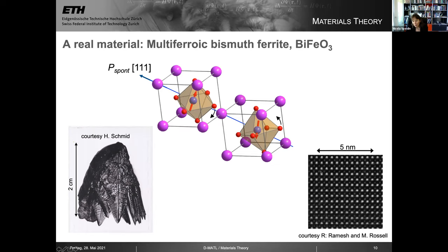And maybe you can see, if you have a good screen, these very slightly lighter dots in the middle, these are the iron ions. One doesn't see the oxygens with this technique. And if you have very good eyesight, you'll see that the iron ions are not exactly in the middle of the bismuth ions. And that's because there's a structural distortion in the material that makes the dipole moment. Of course, it would be easier to see the dipole if we saw also the oxygen anions. So this was a real breakthrough for the field of understanding ferroelectricity and these magnetic ferroelectrics when such beautiful high quality films could be made.